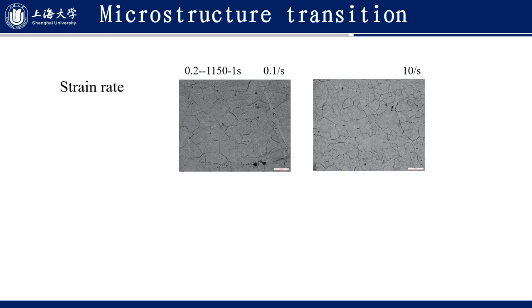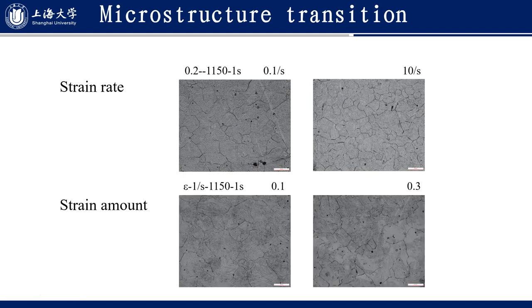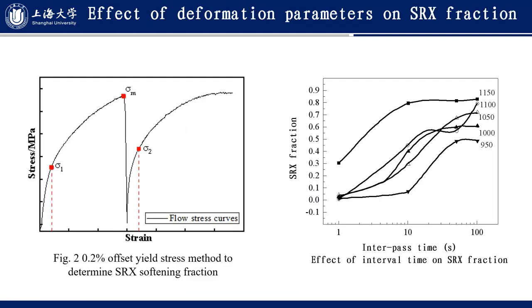For different strain rates, 0.1 per second and 10 per second, the recrystallization behavior is different. And the total strain amount, say 0.1 and 0.3, shows different recrystallization amounts. Now let's see the effect of deformation parameters on static recrystallization fraction.